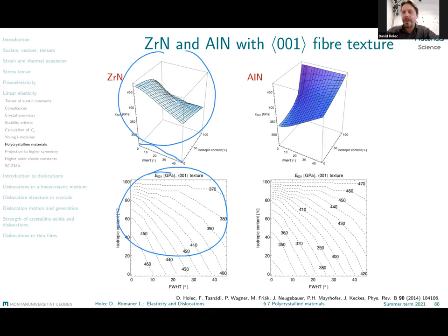What we have on the x-axis is the so-called full width at half maximum of our ODF function. The ODF function is set up so that the 0001 directions are preferably contained. So those might be the orientations of the grains which are there with higher probability. On the y-axis here, I have the so-called isotropic content. So I'm now adding, in addition to my single crystalline grains, also some isotropic material. And this isotropic material is intended to represent the volume fraction of grain boundaries. So if I have small grains and large disordered areas between the grains, grain boundary regions, which have presumably isotropic elastic response, I will have higher isotropic content.